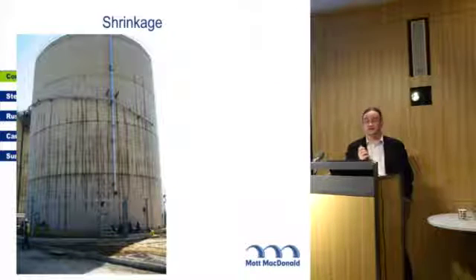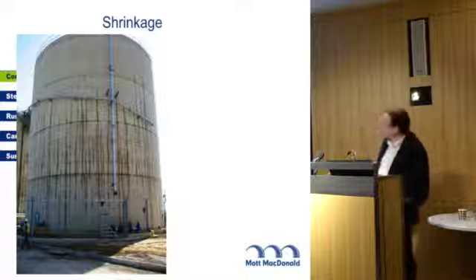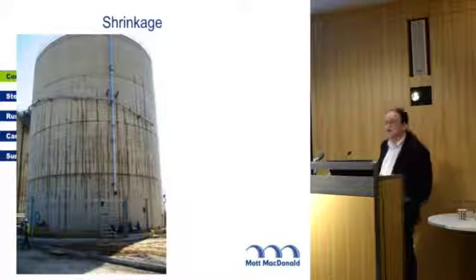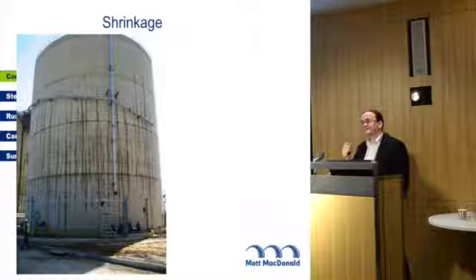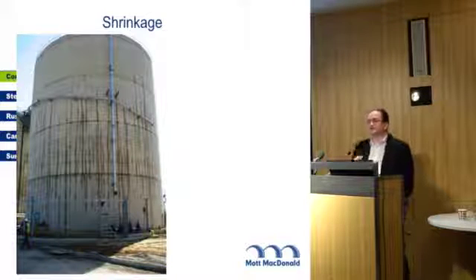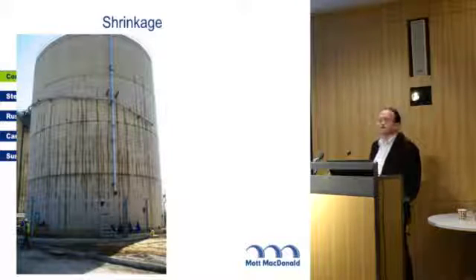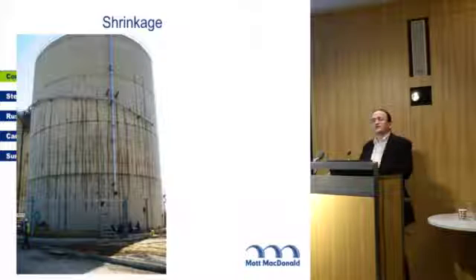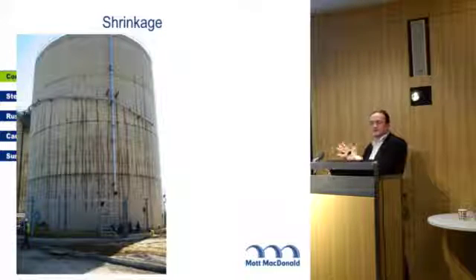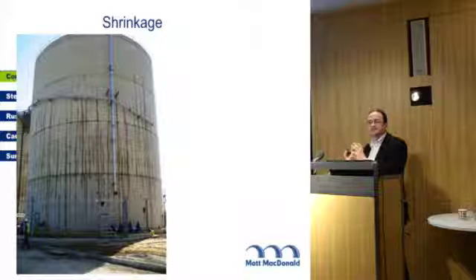This is a water retaining structure, undergoing its water test. Quite a big water retaining structure, there's a bloke. Obviously, if you own this water retaining structure and you're testing it, you're going to be mildly annoyed that there's a lot of water coming out the side of it. But the cracks are nice and evenly spaced, so they show up that it's a materials thing, it's universally shrinking.